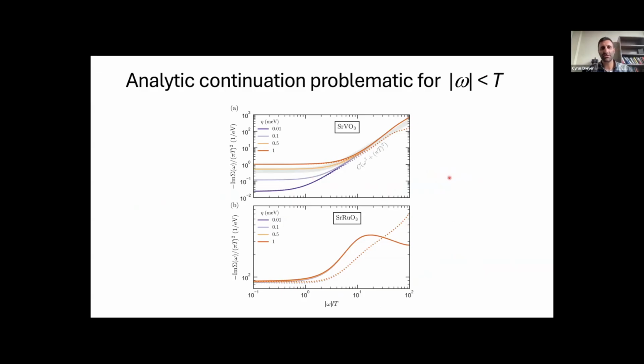So I mentioned that the accuracy in the low frequency regime of the self-energy was not sufficient in the previous plot. One way that we can see this is if we plot, again, the imaginary part of the self-energy, the Pade analytically continued self-energy from the QMC, over pi T squared versus omega over T. And we're plotting it versus the eta parameter, which is the parameter of the analytic continuation to omega plus i eta. What we would expect is if we decrease the eta parameter, we should see some convergence of the analytic continuation. But for strontium vanadate, and we see the same for strontium ruthenate, as we decrease eta, we just decrease the imaginary part of the self-energy at low frequencies.